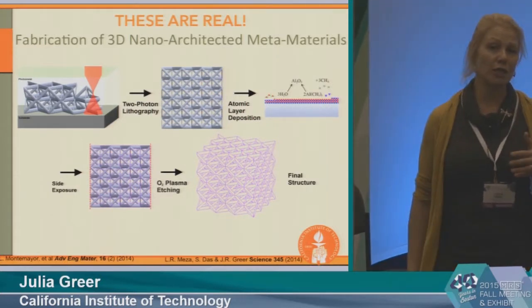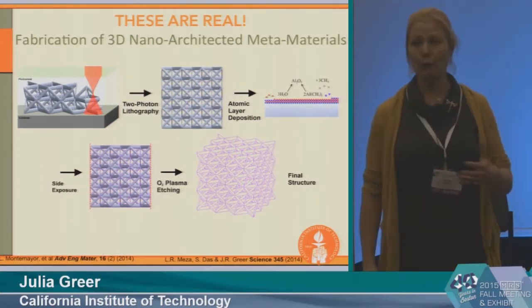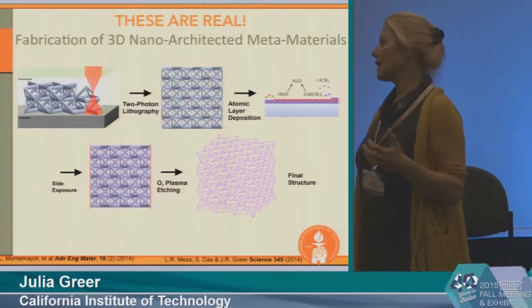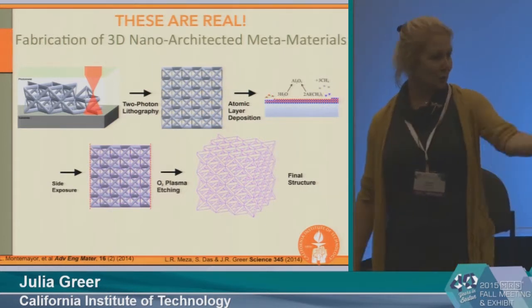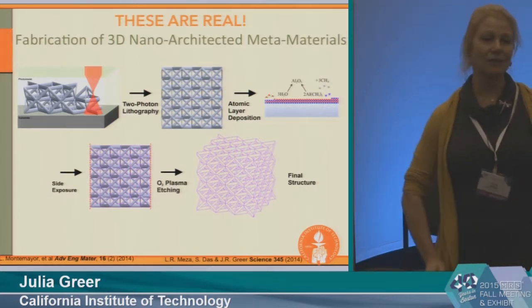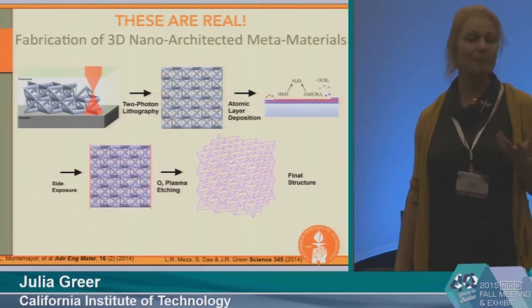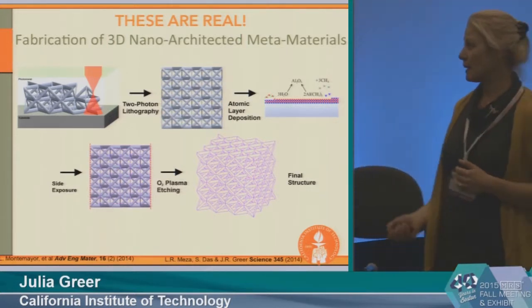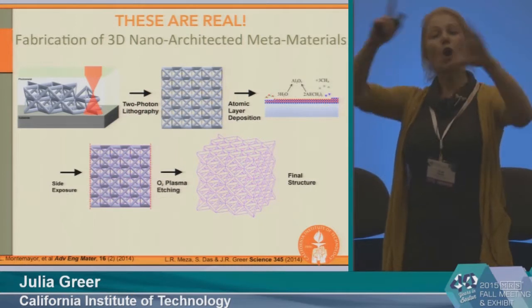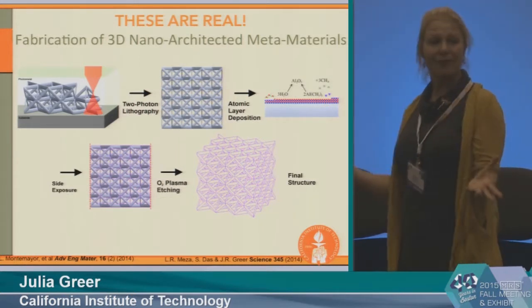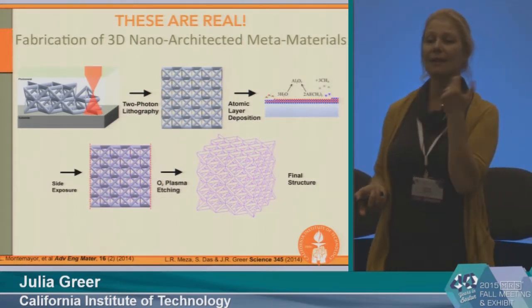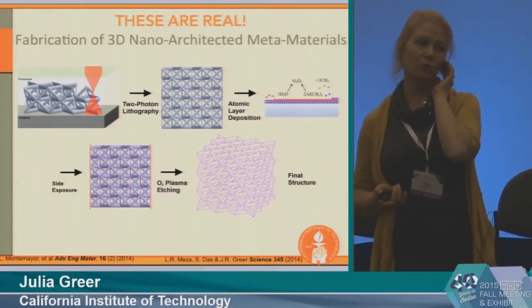Or if you're interested in a metal, you can use sputtering or electroplating. If you're interested in gallium nitride or some kind of solid state lighting device, your best bet is to go to MBE or MOCVD or something like that. And after that, we coat the entire structure with this material of interest, only with a very thin layer of it, maybe up to 100 nanometers, no more than that.